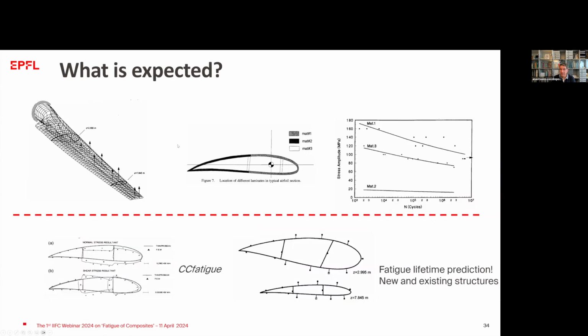So what is expected? And I'm close to summarize. What do we expect actually with these fatigue investigations? It is expected to actually take out this red line. There is a red line between the observation, the models that we have for our structures, the models regarding the material used in structures, and the material data that we collect. And here, if I remove this line, I have the calculation of stresses in the structure. I have theories like this, what we call a CC fatigue is a theory that we are developing internally here in the group that can give us actually a safety factor, if you like, to call these dots here for every section or every position on the blade.